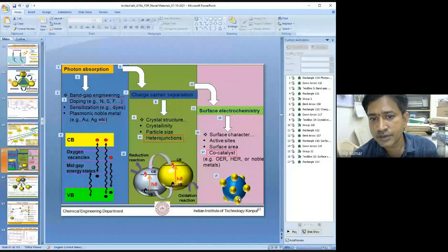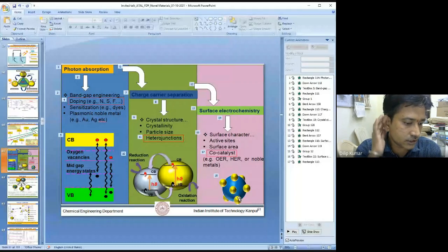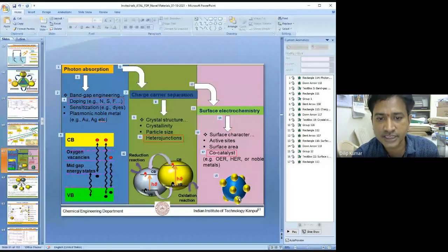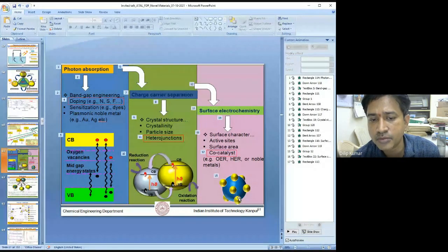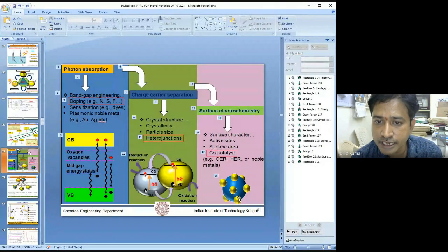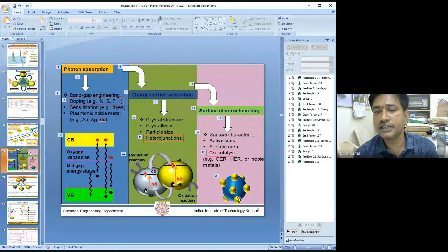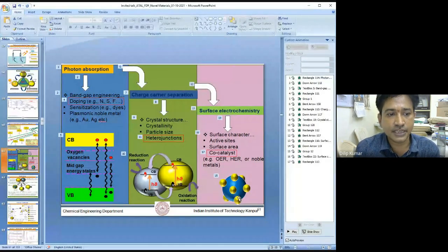And the other part of the surface electrochemistry is how do we improve the, because after even separating the charge carriers, we need fast extraction of species for the reactions. Maybe it's an oxygen evolution reaction or hydrogen evolution reaction. Maybe if you increase the surface areas or active sites or some co-catalyst like platinum, gold, which can quickly take the electrons or the holes, and they can close the entire photoelectrochemical water splitting reaction.